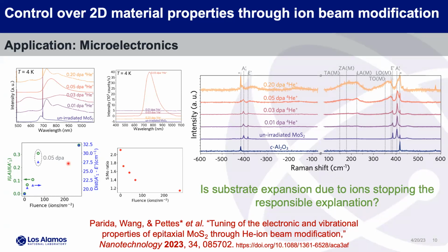Basically you're putting alpha particles through a foil of a certain material, and depending on the charge state, that'll give you much higher energy. So that's one capability in the Ion Beam Materials Lab. Another capability is an implanter, which is basically what industry uses to implant silicon. That's what we used for this study. For this, we wanted a light ion, so we're using helium, just regular 4He+, and we're implanting it at certain DPAs.